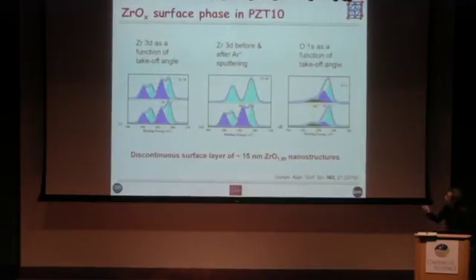Looking in more detail at the 10% sample, this is done as a function of takeoff angle, so we actually go to more glancing emission here, and the second high energy component has increased, confirming its surface nature, so it's correlated with these nanostructures. We've then sputtered the surface, and this second component disappears. So once again, we've removed matter from the surface. This corresponds to those nanostructures. And finally, the oxygen 1s, when we go to more glancing emission, again, this second component, which is related to that surface phase, the surface nanostructures, has increased in intensity. So we can do some quantitative analysis, and basically what we have is a discontinuous surface layer of 15 nanometer diameter ZrO1.89 nanostructures, almost ZrO2.